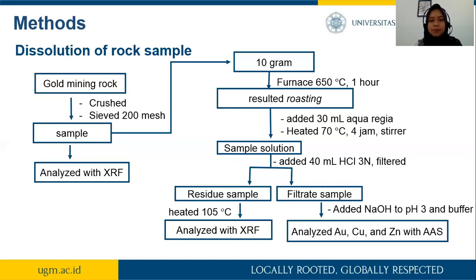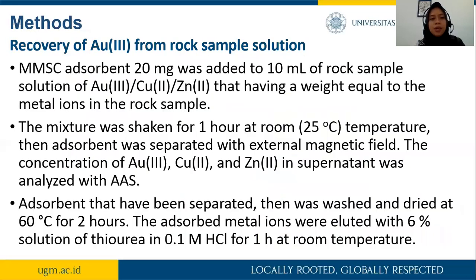hydrochloric acid. And the third, we apply a recovery of Au3+ from the rock sample solution. There is a 20 milligram adsorbent added to 10 milliliters of rock sample solution. The mixture was shaken for 1 hour at room temperature. And then the adsorbent that had been separated was washed and dried at 60 degrees Celsius for 2 hours. The adsorbed metal ions were eluted with 6% solution of thiourea for 1 hour at room temperature.